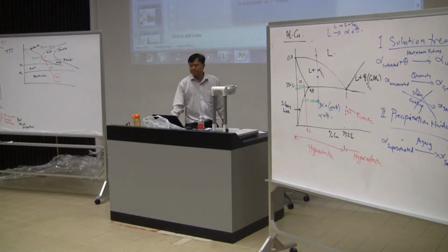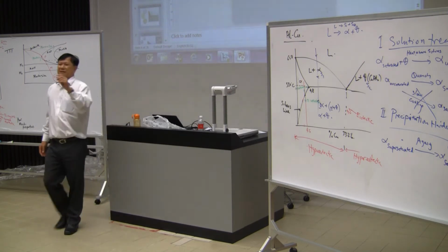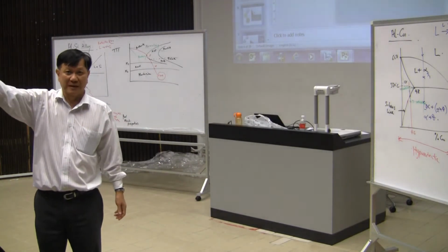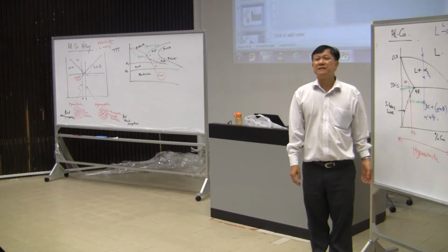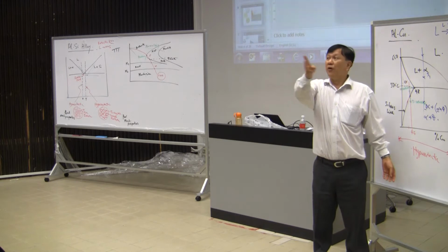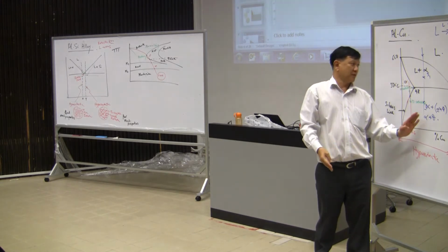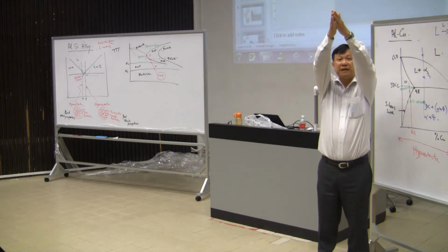Sir, is this one reversible? Tempering is not reversible. No. Hardening is reversible. You can redo hardening. You can redo normalizing. Why? Basically, if this is an iron carbon diagram, for hardening you are actually austenitizing. That means you start all over again from austenite.